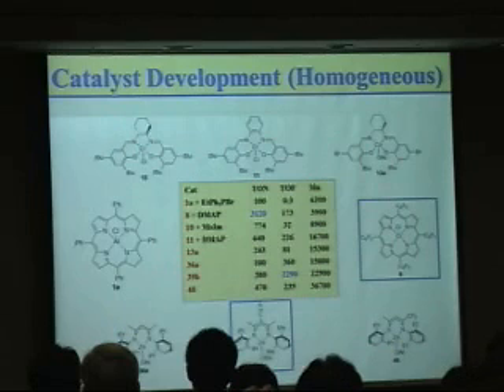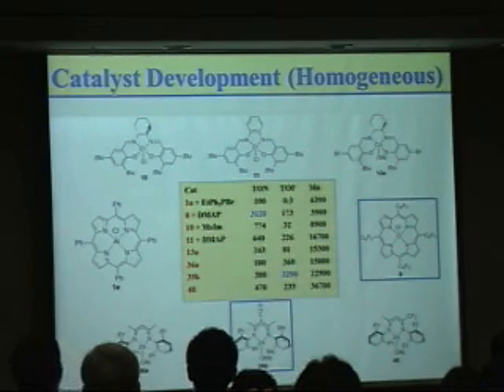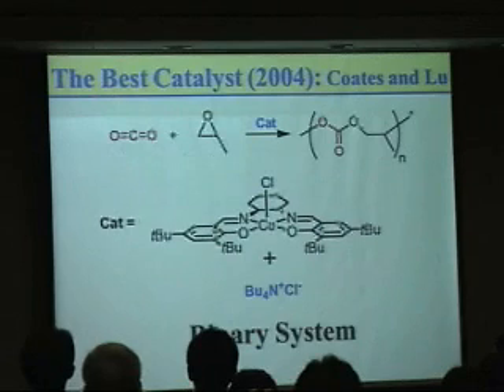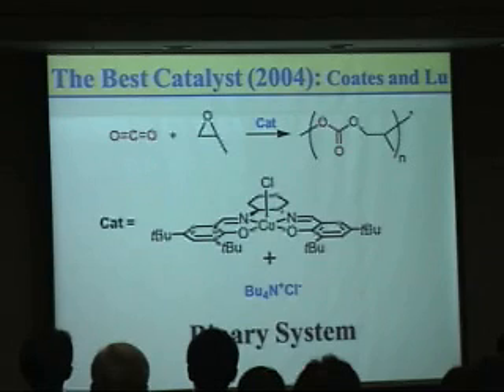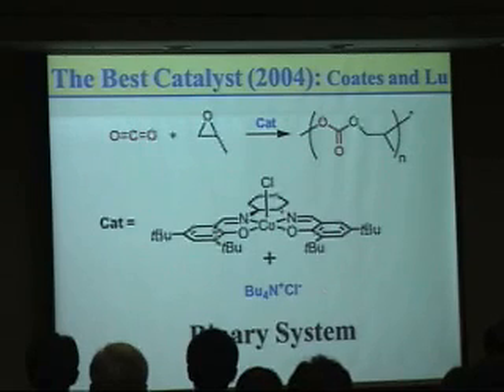So lots of homogeneous catalysts have also been introduced, and the catalytic activity in terms of the activity and molecular weight was not satisfactory. The best catalyst when I got involved in this project was the binary system composed of salen cobalt complex and quaternary ammonium salt. This salen cobalt complex was introduced by Professor Coates at Cornell University. Very soon later, Professor Lu in Dalian University reported that addition of 1 equivalent of quaternary ammonium salt improved the catalytic activity almost 10 times.